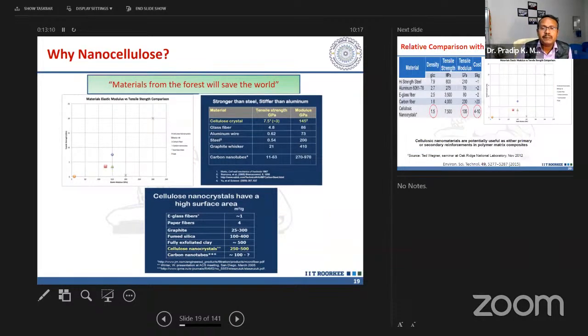So if I compare the material characteristics from the mechanical point of view, if you see tensile strength, we are very much higher, I'm talking about specific tensile strength. You are much higher than carbon fiber or stainless steel. It is stronger than steel, stiffer than aluminum. Cellulose nanocrystal, what I told you, 7.5 GPa; cellulose nanofiber, generally 3 GPa is what we get as tensile strength. And the modulus value you can realize is 145, whereas carbon nanotube has very good tensile strength and tensile modulus also. But I'll be telling you in different aspects why cellulose nanocrystal is more important than carbon nanotube or nanofiber.